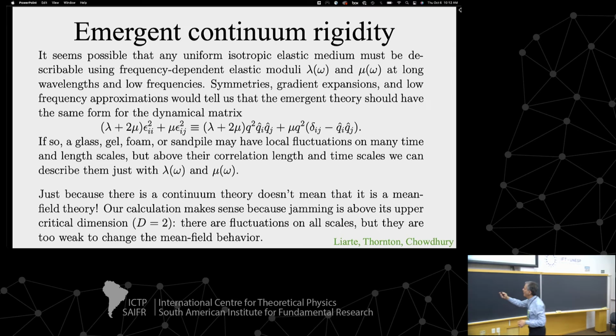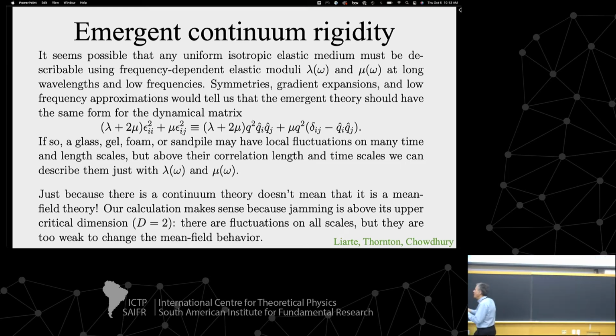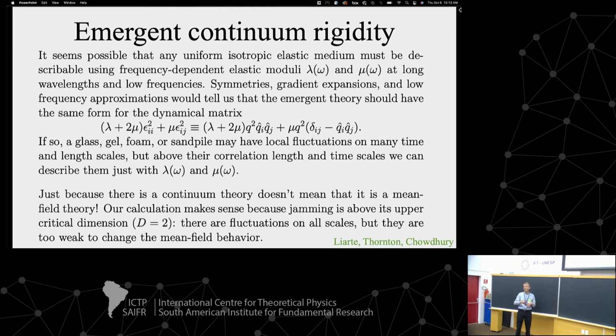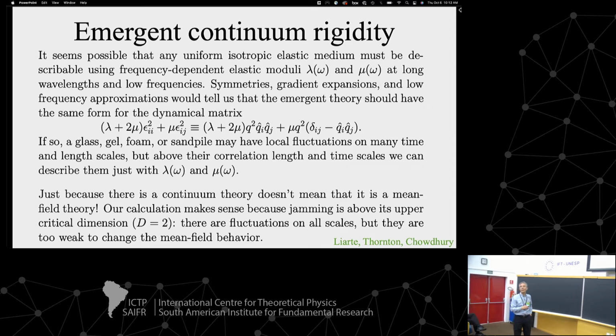Okay. So it seems possible that any uniform isotropic elastic medium must be describable using frequency-dependent elastic moduli. I don't know that that's not true. Doesn't mean it's true. And I'm clearly making assumptions that there are no long-term memories in the material, and that it's in a stationary state. Real glasses have aging and things like that, but they age so slowly that they're well approximated by the sort of instantaneous behavior, and maybe all of that can be described by a frequency-dependent modulus. Could be.